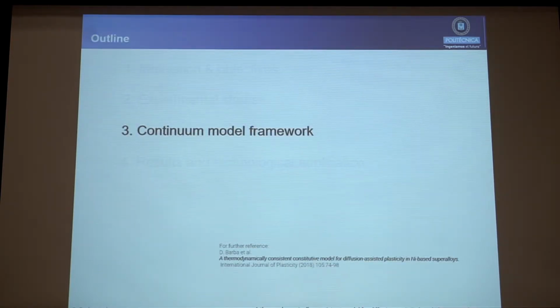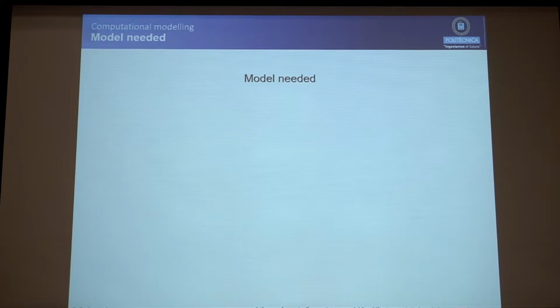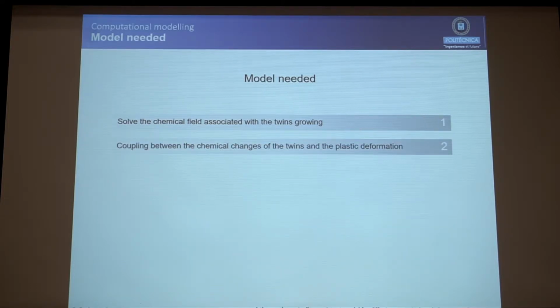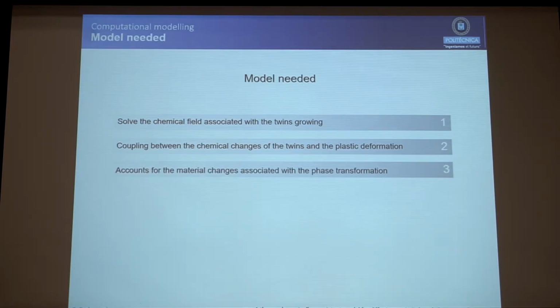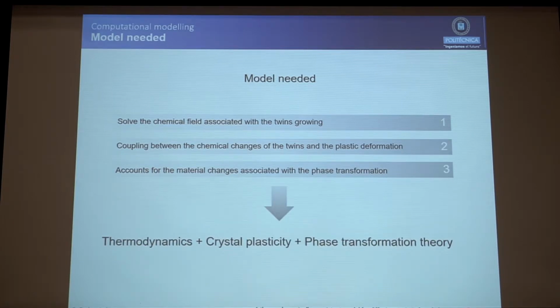So I'm going to get into the continuum model framework. The model that we need, clearly, needs to solve the chemical field around this twinning formation. It needs to couple this chemical field with the plasticity that is happening, because as I said, the chemical composition is changing the stress required for the dislocation to shear the precipitate. And finally, we need to account for the material changes as the phase transformation is happening, because as the microtwin is forming, the new material doesn't have the same elastic properties as the parent phase. So we need to take all this into account. So we need to couple together thermodynamics, crystal plasticity, and phase transformation theory in a unique framework.